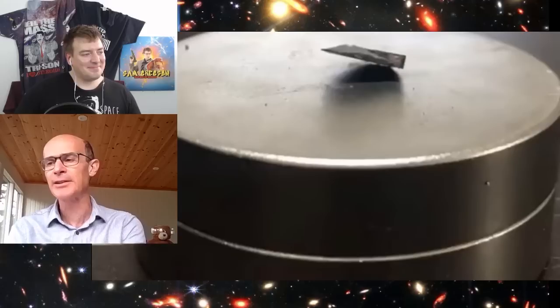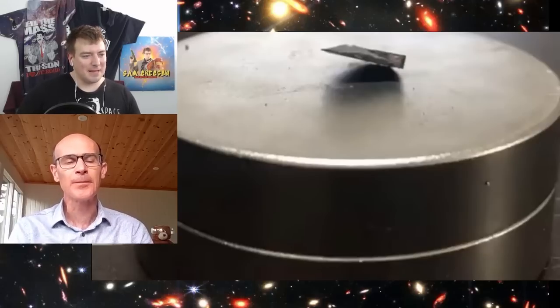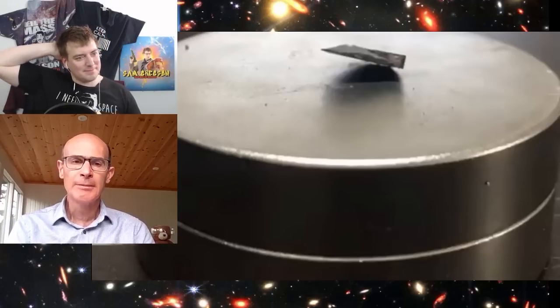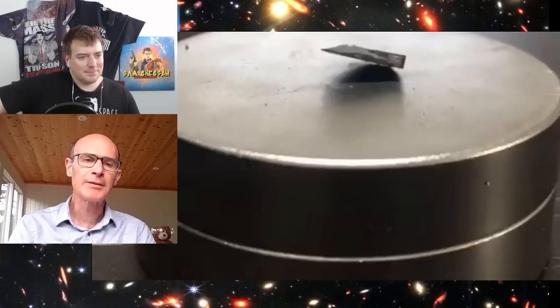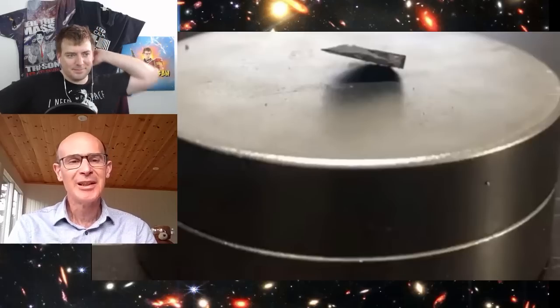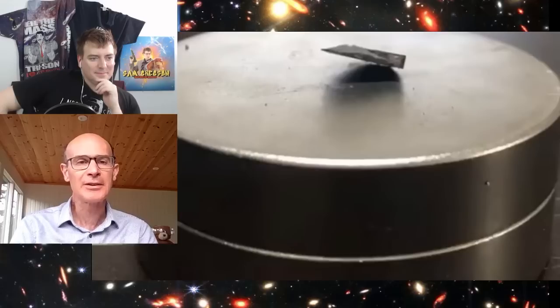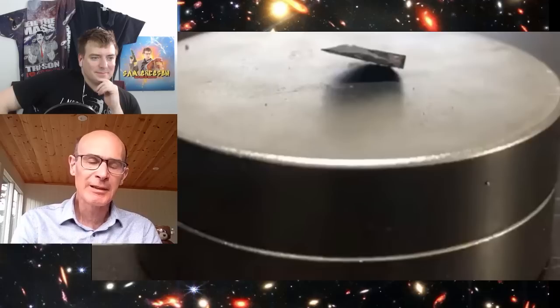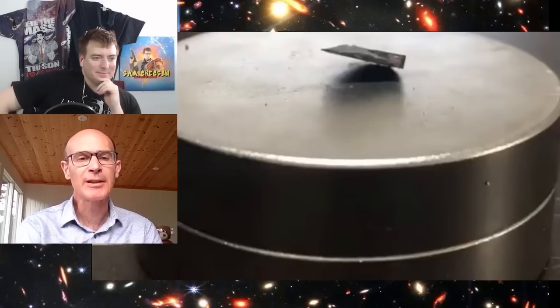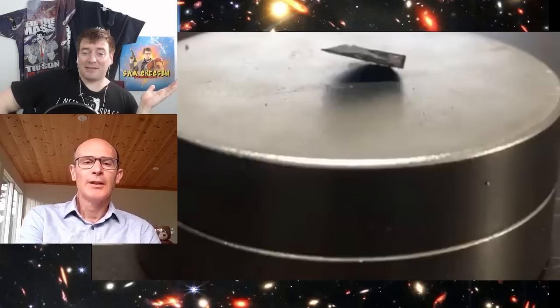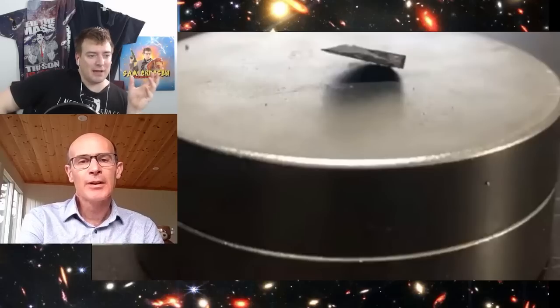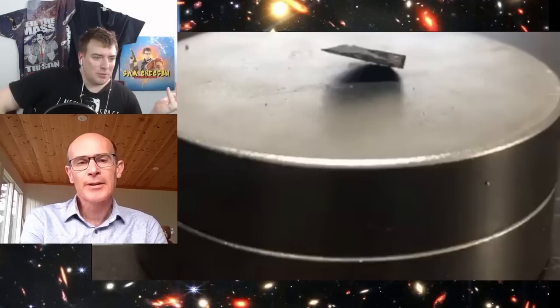And there's this uncertainty. For a chemist, there's uncertainty about what the composition is. As far as I can see, there hasn't been any microscopy of any type carried out on these materials. Especially if it's a composite, that would be something to investigate. How does the composition change across that piece that's shown there on top of those magnets? What is it? Is it apatite embedded in copper sulfide or something like that, or are there other phases present? Which could be interesting in itself, right? If there are different interesting phases in there, or interactions between phases that are doing strange things, that could be interesting of itself, naively, to someone who's not an expert in the field. No, I think that's right.